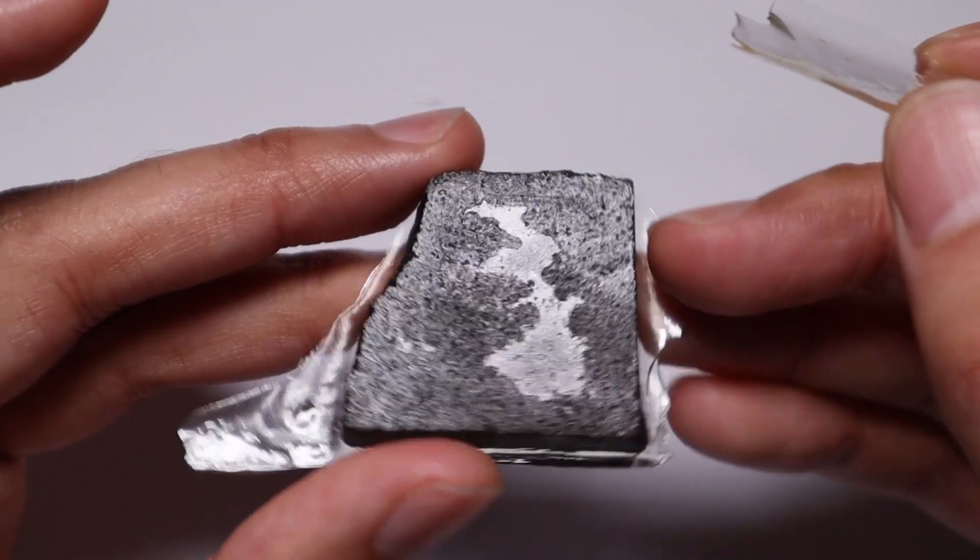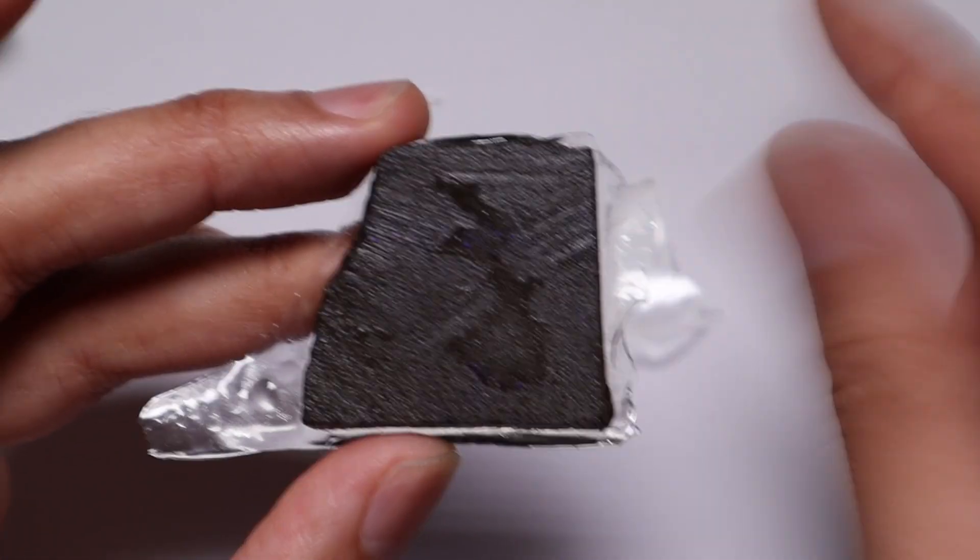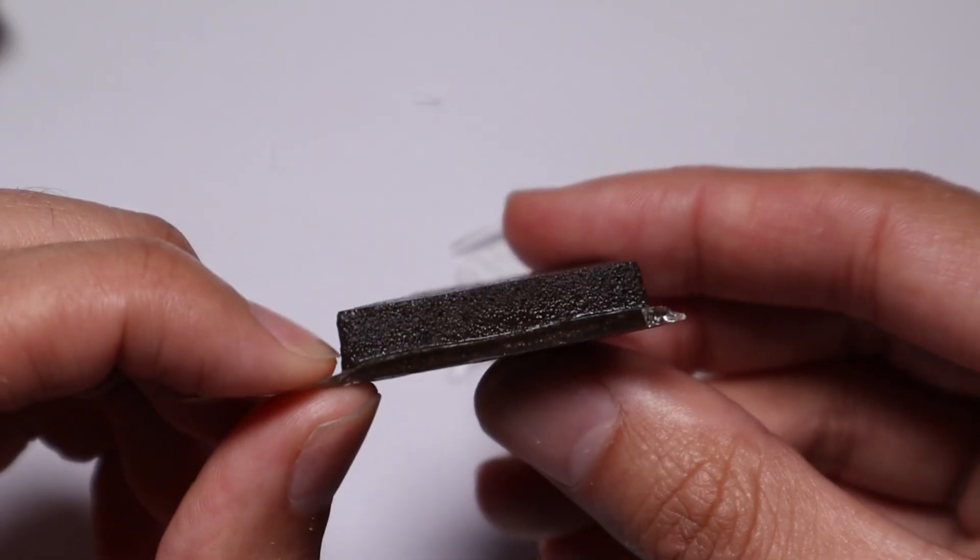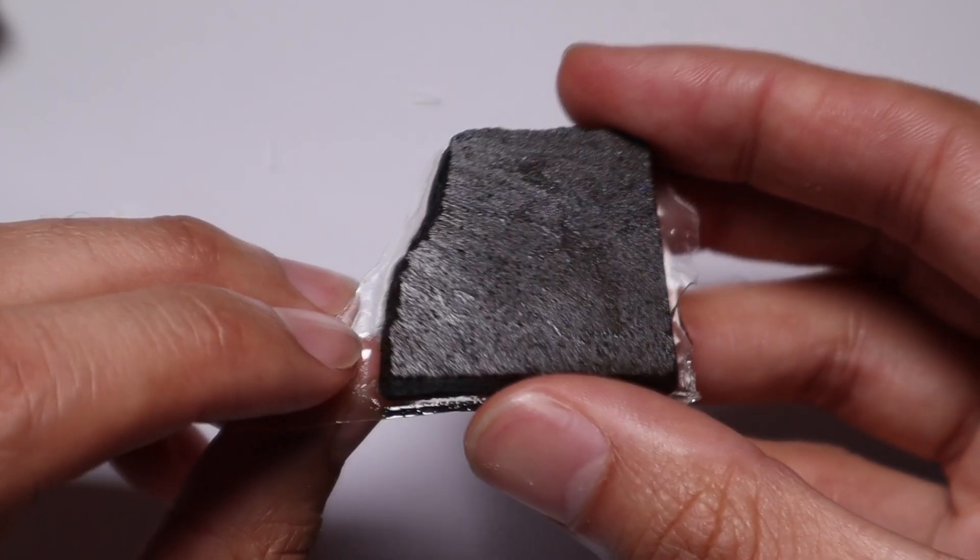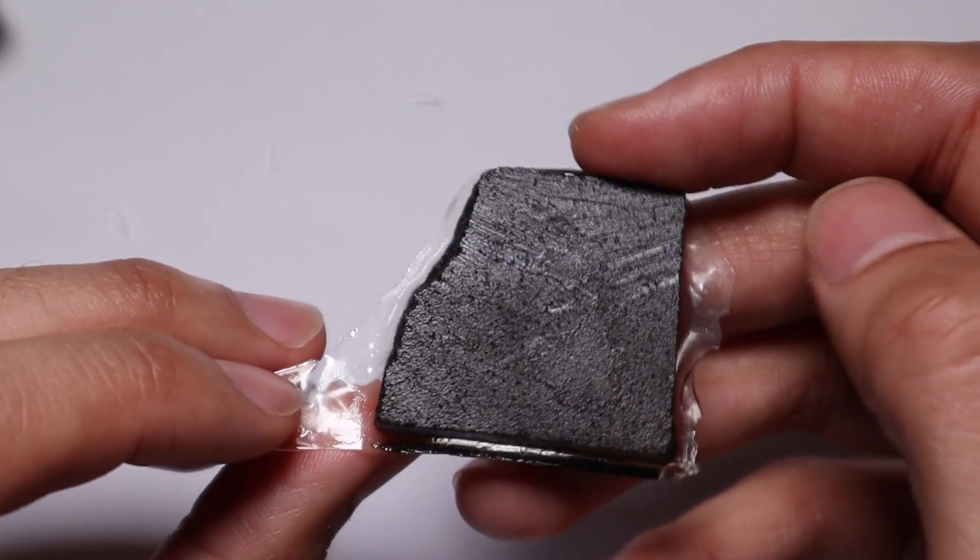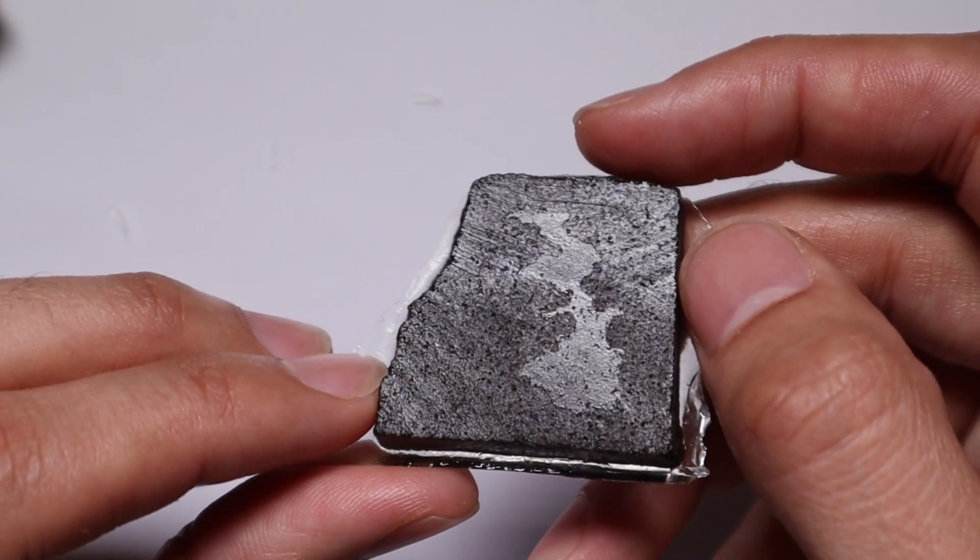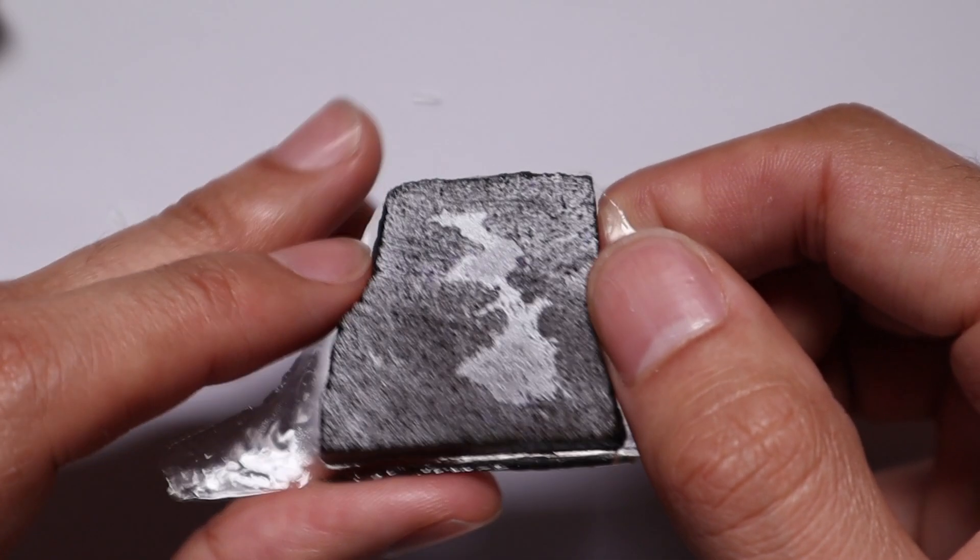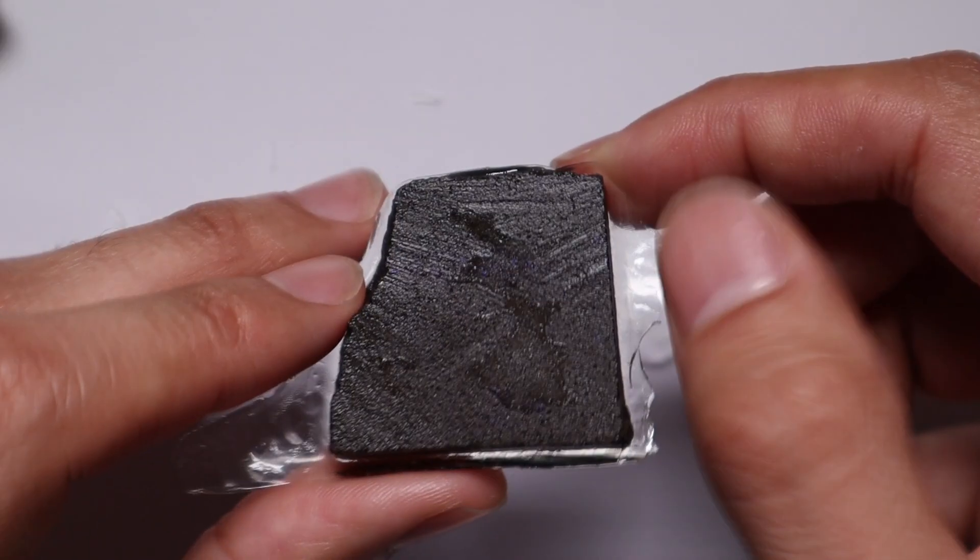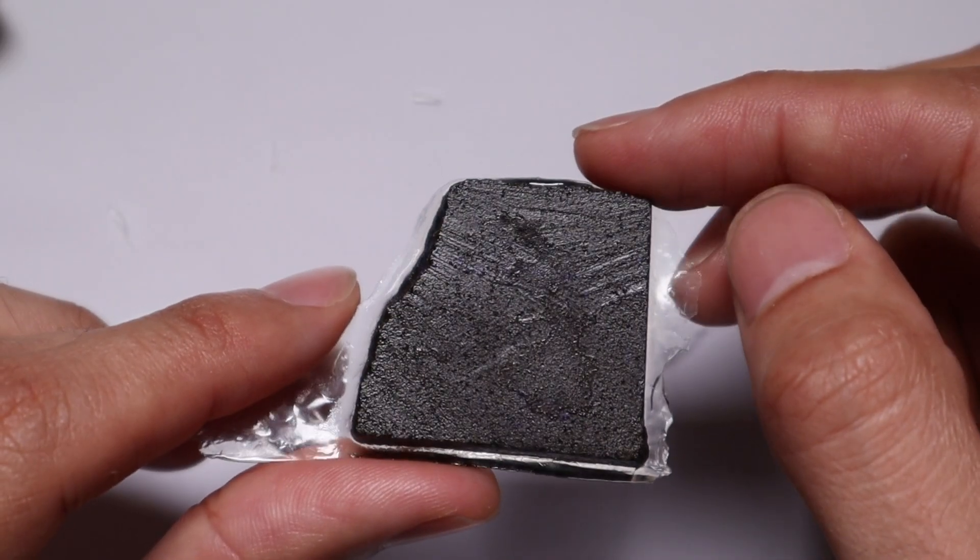Sometimes they'll be down because of sterics, but you get the idea. It's going to form a really long chain. And that really long chain is this. I'm not the biggest fan of polymer chemistry, but it is pretty fun to mess with and it does work. So this is all inside the stone. So this stone started off at about 15 grams and it absolutely launched. Don't be surprised if you triple your weight of your stone. You're going to at least double it depending on how porous it is. If it's really not porous, like Andamooka, it might not grow that much. But if it's a porous Winton fairy opal like this, it is going to go absolutely bonkers. It is super heavy now. So it does soak up a lot of material and it does get in there and I can see why it's really good for wood, but there are drawbacks when it comes to stone, as you can see.